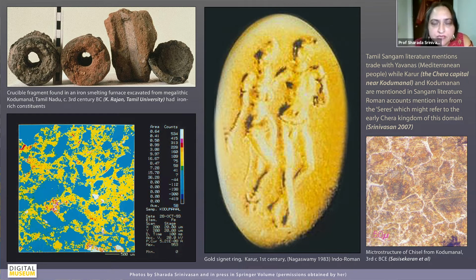And I had done microstructural analysis and also used a technique called electron probe microanalysis with dot mapping, which means that you can actually map the elemental concentration across the cross section, and you can see where the metallic prills of iron or steel or whatever are concentrating in that cross section. So this also confirms that these crucibles were used for ferrous metal processing. And there's also a microstructure of a chisel here from Kodumanal, which has a similar honeycomb structure related to high carbon steel.